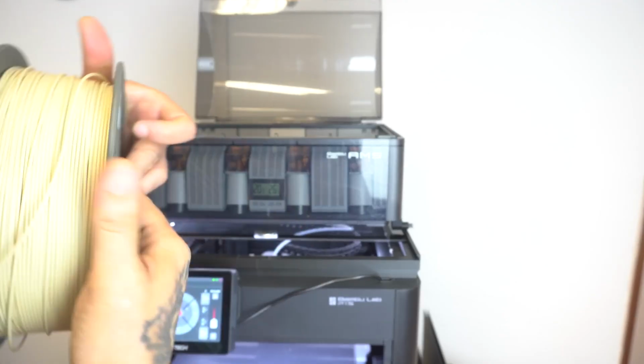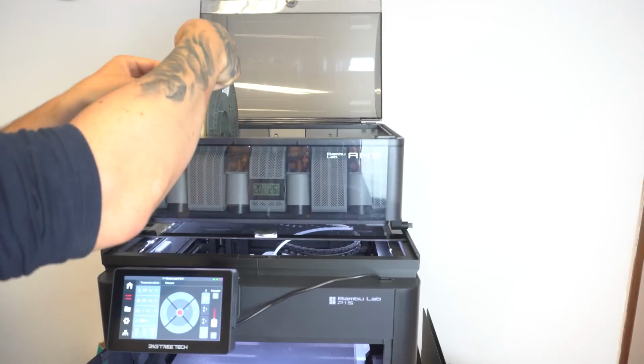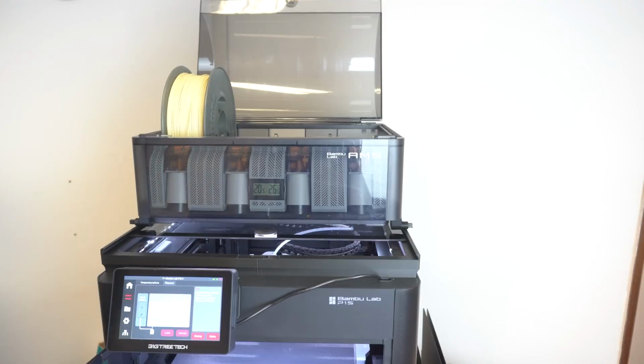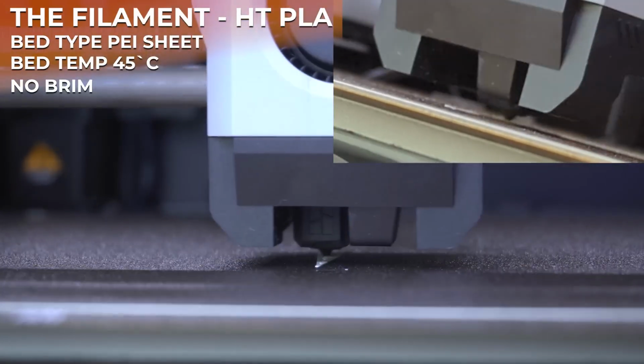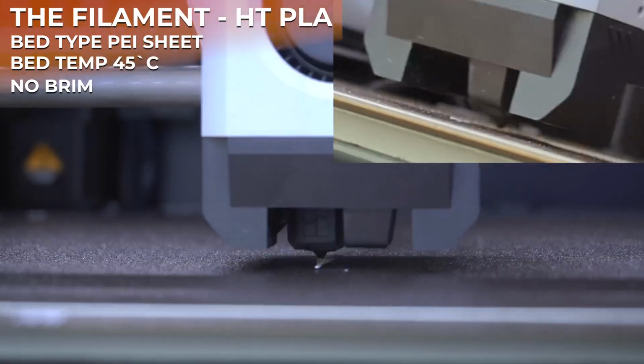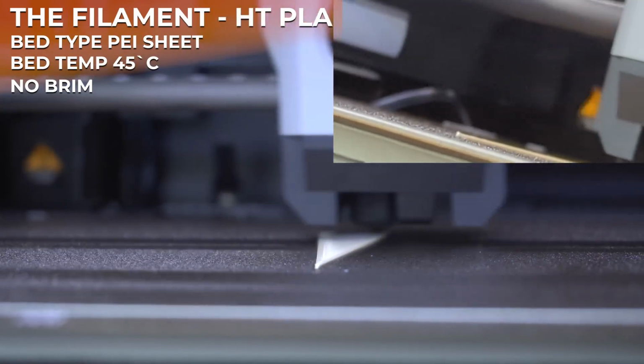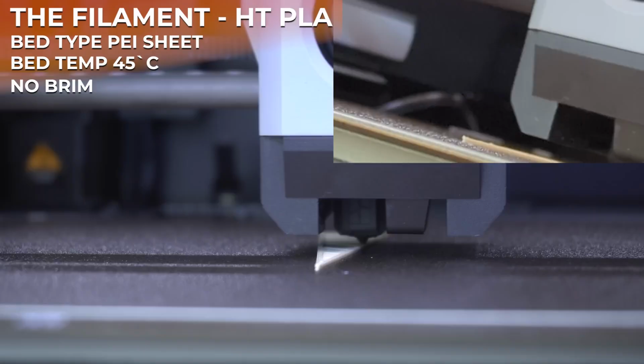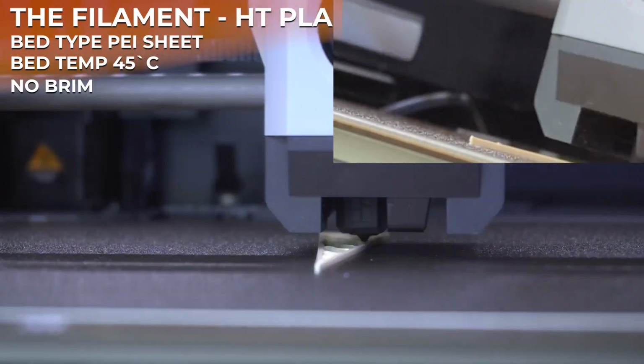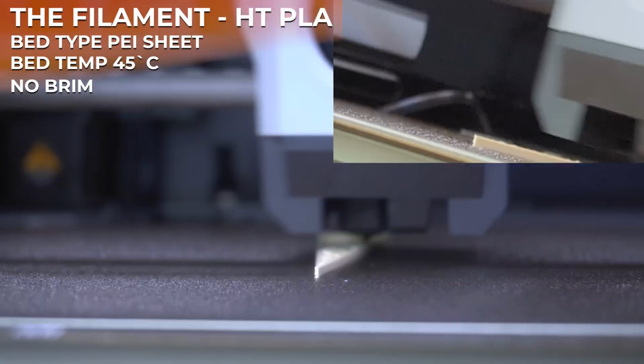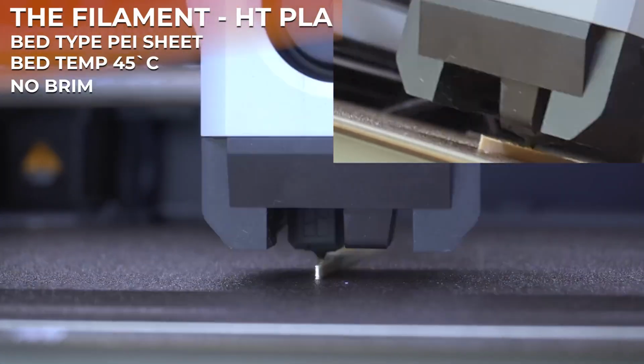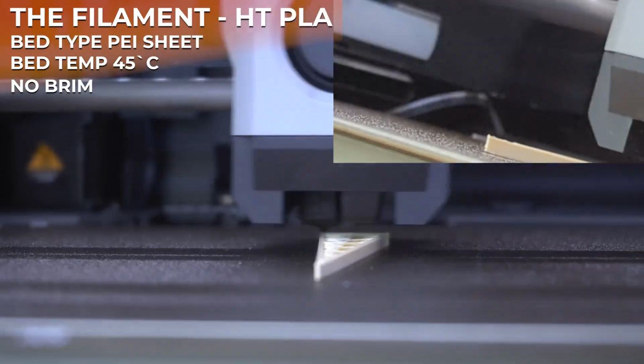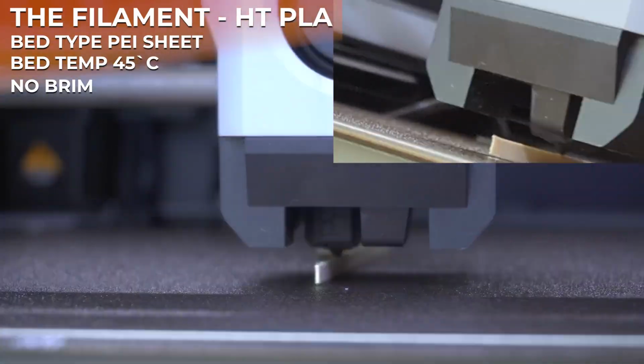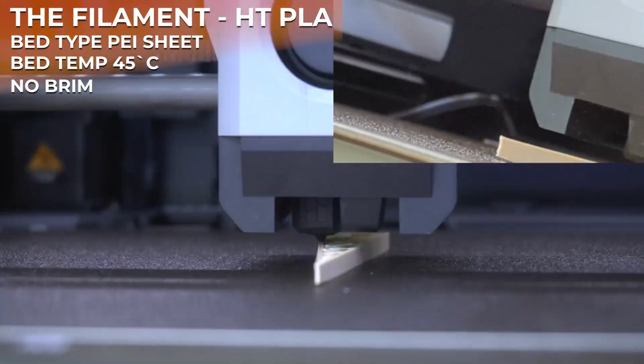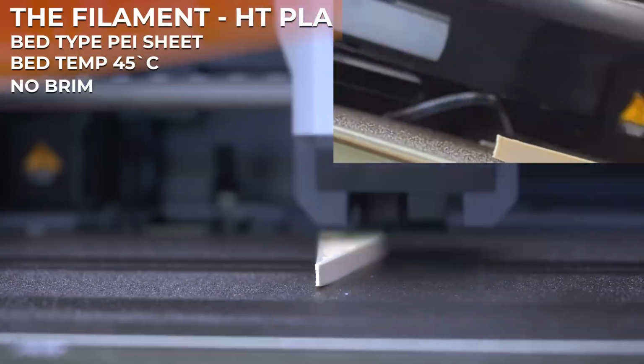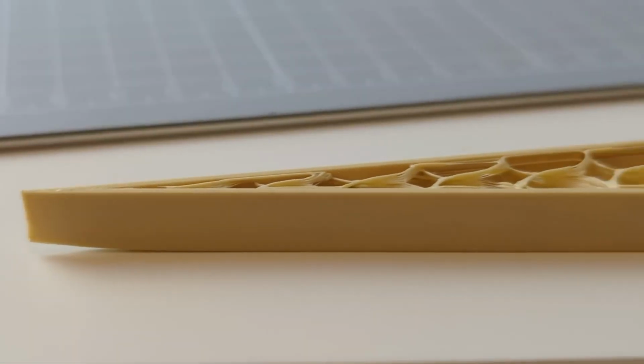And now we're loading the filament HT-PLA in the AMS, ready for the warping and bed adhesion test. The bed temperature is set to 45 degrees Celsius and no brim. Even this one, it looks like it's going to hold up, but after a while you will see that the front is warping. We can stop the print and inspect it. We have a really bad warping at the front and just a tiny bit in the back.